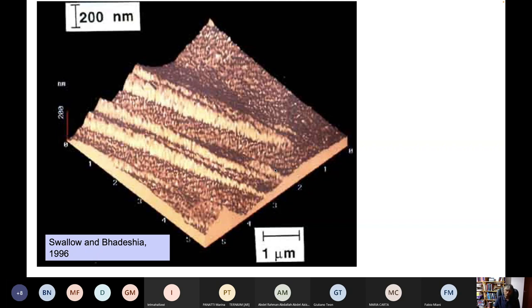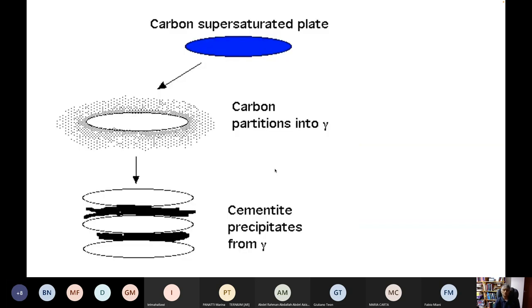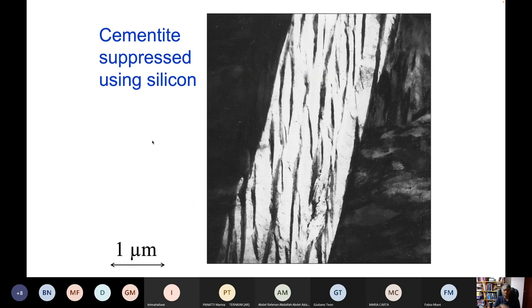We need to introduce a work hardening capacity. As in my lecture on TRIP steels, we basically generate a structure which consists of plates of ferrite and carbon-enriched retained austenite. We stop the reaction using silicon. The deformation-induced transformation of the austenite automatically gives us a work hardening mechanism, because when it transforms under the influence of stress or strain, it will produce hard martensite — in other words, you've hardened your structure to local instabilities by the TRIP effect. Here is the structure: beautiful fine plates of bainitic ferrite separated by films of carbon-enriched retained austenite. But the scale here is one micrometer and I want to produce a nanostructure.